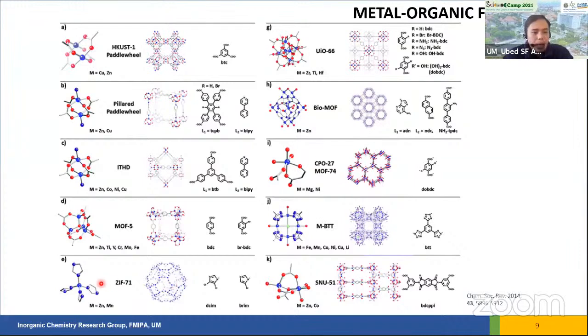Or maybe the MOF-5 that we learned before. The MOF-5 can be formed by zinc or titanium or vanadium or chromium or manganese or iron. We can use these metal ions to form such a type of metal cluster. And if we use such a type of organic ligand, that is terephthalic acid, we can get a 3D structure with pores inside. So it's very different. Many structures can be formed.